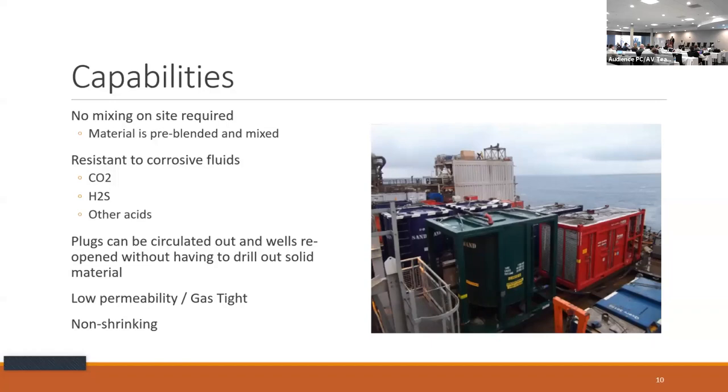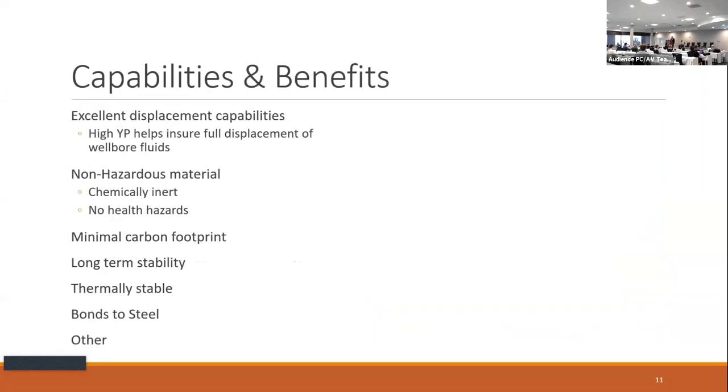If you use it as a plugging material, you can just circulate out the plug whenever you want, or the well will be considered abandoned permanently if you leave it in place. Low permeability: they've tested it in annular conditions for gas flow, and because of the particle size distribution, there's essentially zero permeable flow through this material. And guess what? It also doesn't shrink. There's no hydration volume reduction.